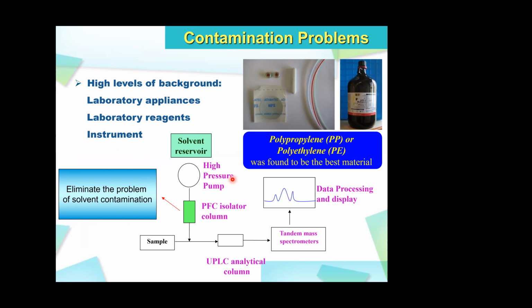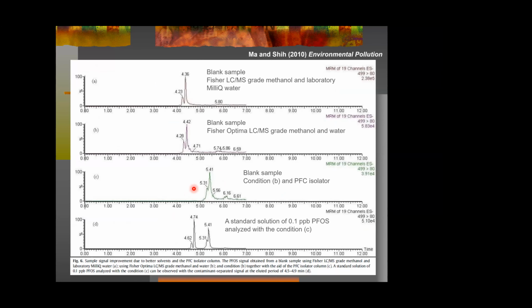So it's very difficult. One of the things that we used at the time, as one of the very early groups in the world using this technique, is a PFC isolation column. The column basically tries to stop the signal coming from the instrument. This is one example. Even if I have a blank sample, completely nothing, the methanol by itself in the LC already shows this peak. We may use some kind of methanol that has a relatively lower background signal, but it's still there. Now we use the PFC isolator columns.